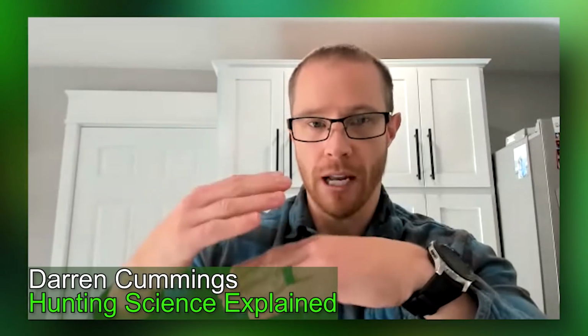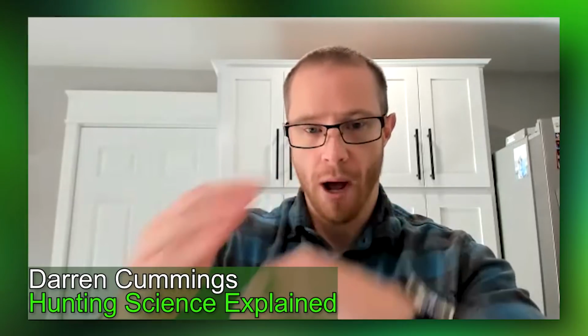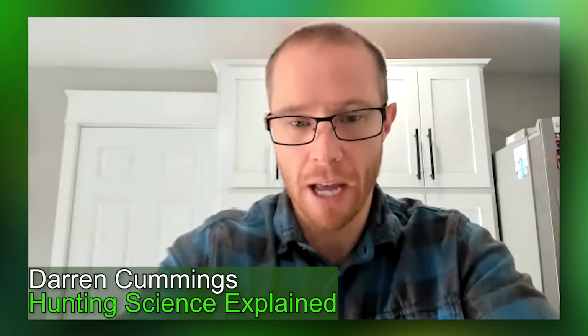And all these micro cracks line up. Now you get the edge splinters and the individual little things popping up. And if you look at the pictures you sent me, this is exactly what it looks like. It basically delaminated. So what happened was it wasn't the fibers that failed, it was the resin that holds them together.